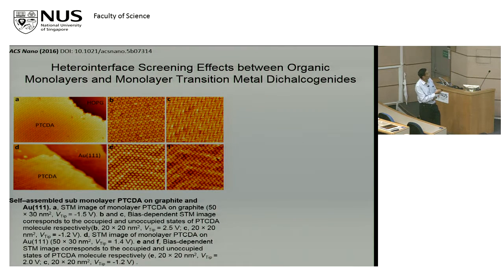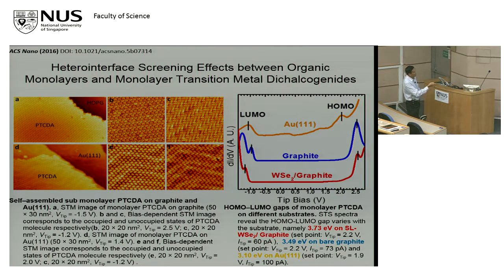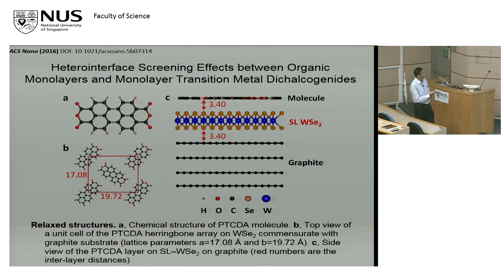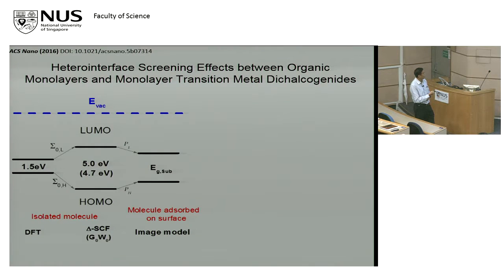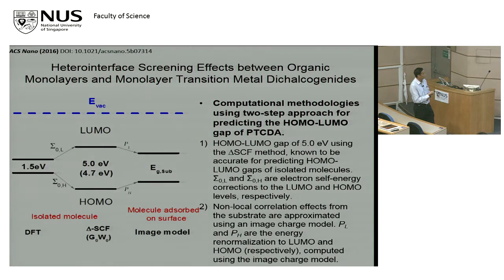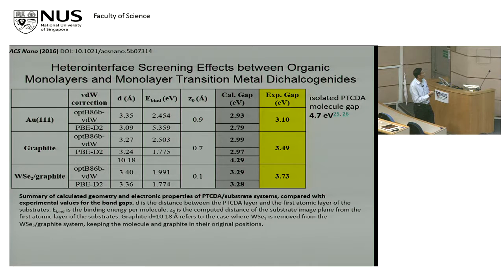We can look at the electronic structure and compare them if we put PTCDA on different substrates, and compare why the electronic structure changes, and explain through theory, which he's also doing with Suing's supervision, the differences in the electronic structure because of the different screening effects of the different substrates used. This is just a model, the computation that's done. I won't go through this, or I shouldn't have shown all this. But it basically predicts, with some systematic error,